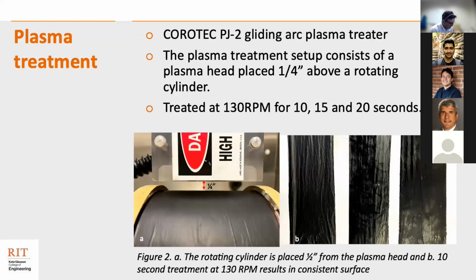We make use of a COROTEC PJ-2 gliding arc plasma treater for our research, and the setup consists of our films, as shown in figure 2a, wrapped around a cylinder which is placed 1/4 of an inch below the plasma head. The cylinder is rotating at 130 RPM, and the films are treated for 10, 15, and 20 seconds. We had to rotate the films because plasma treatments generally increase the surface temperature, and we didn't want these films to melt. That's why we wanted it to continuously rotate so that the films have the time to cool down.